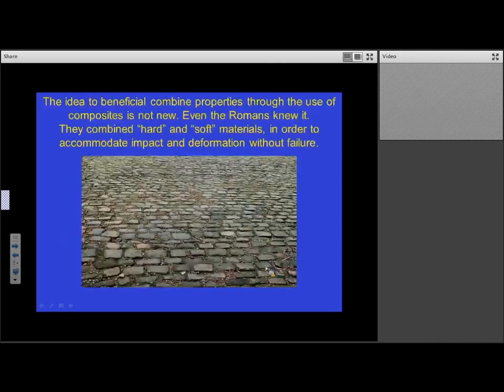Now this is the other area where the road to nowhere comes in, because even the Romans knew that the best way to create a wear-resistant surface was to have hard blocks separated by a compliant, if you like, grain boundary phase, which can accommodate the deformation. So as the chariots rode over this road, if that was a solid piece of stone, it would just break up and fail. Whereas with this kind of cobbled road construction, it can accommodate the loading and the deformations without failure. So this is where we take that analogy of the road to nowhere a step further, and we use this concept to help us design nanocomposite coatings.